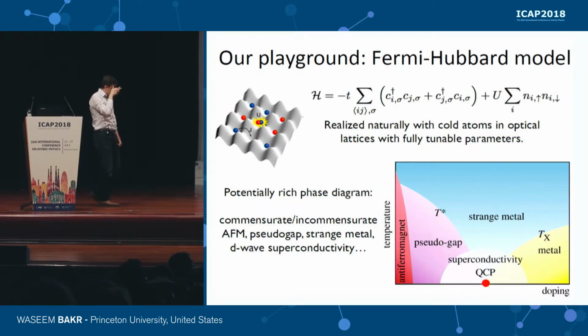The playground I want to use for exploring transport in a strongly interacting regime is the Fermi-Hubbard model. We have in the lab a 2D square lattice, where we put two species of fermions. These fermions can tunnel around between nearest neighbor sites, as described by the first term of this Hamiltonian. And whenever two fermions of opposite spin land on the same site, there's a strong repulsive interaction.